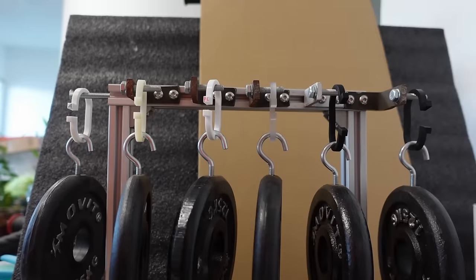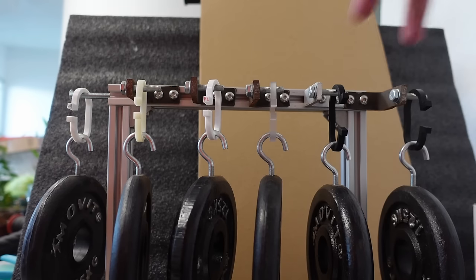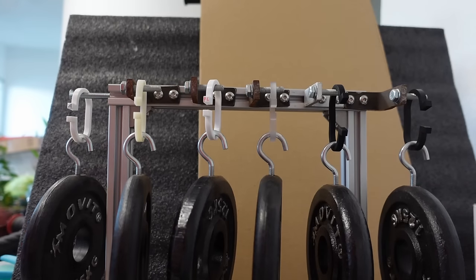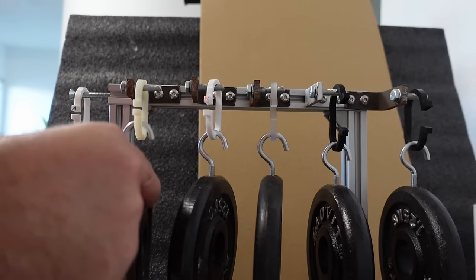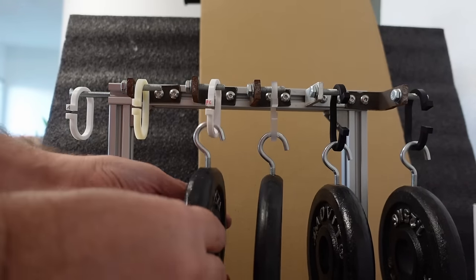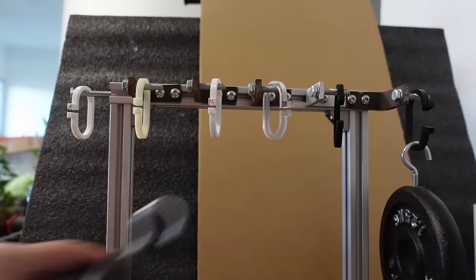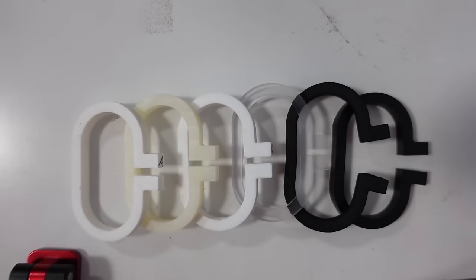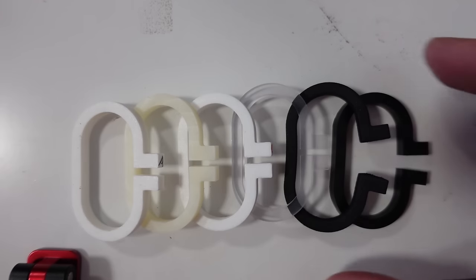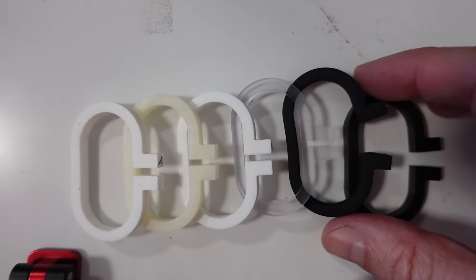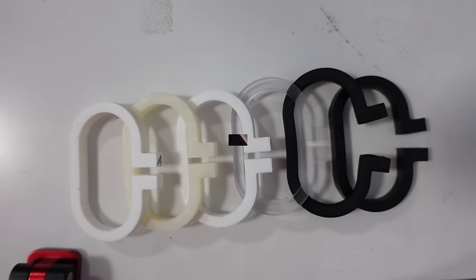This is the last day of the testing. A lot of deformation on parts from the nylon, and with these four, very minimal additional deformation. And now let's remove the load. And after approximately five minutes, almost no deformation on these four parts, and quite a big permanent deformation on two parts from the nylon.